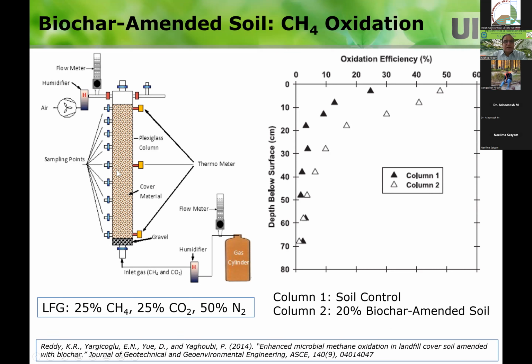And then based on the depth below the surface, you can see the oxidation efficiency of the methane. So this is column 1. You can see that the oxidation rate increases significantly with the depth up to a certain depth, because these microbes need oxygen. So the maximum methane oxidation happens near the surface, and as you go deeper, it could be oxygen limited conditions, and then it may not be as efficient. But overall, you can see a lot of methane is oxidized in column 2 with the biochar. And this is the paper that you can find a lot of details about it.